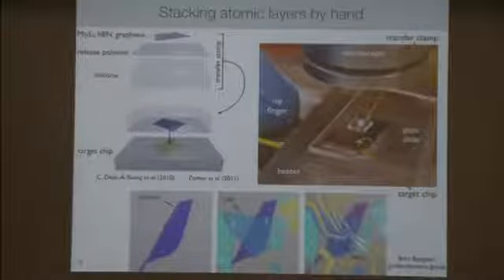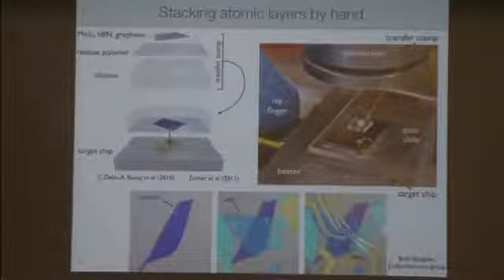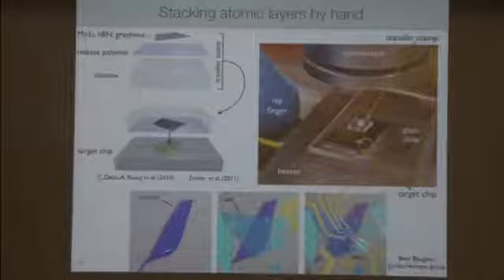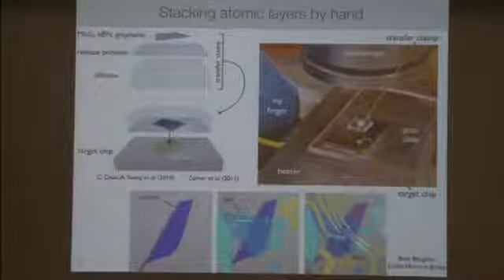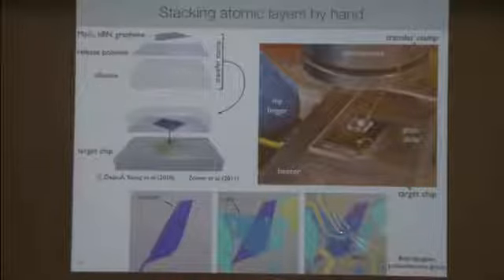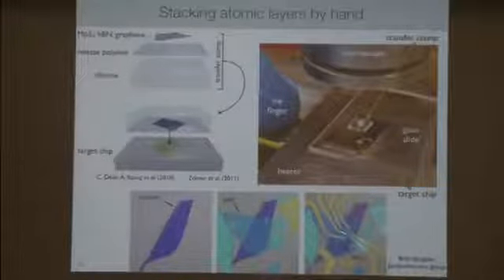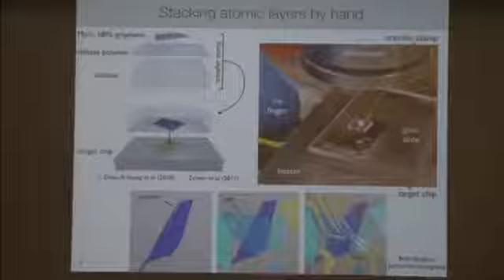And here are some optical microscope images of one such device made by Britt Bogger, who's a graduate student in the Rio Herrero lab. So it starts out with deposition of graphite on a silicon chip, then hexagonal boron nitride is added, then a layer of molybdenum disulfide, and finally gold contacts are applied to the molybdenum disulfide so we can do electrical measurements on that semiconductor in this heterostructure.